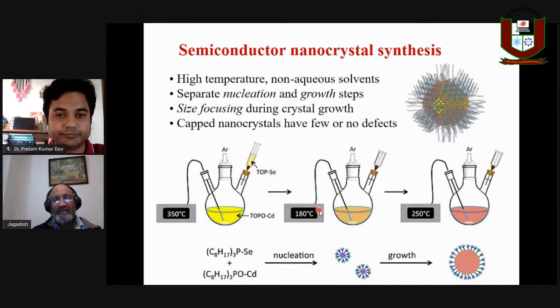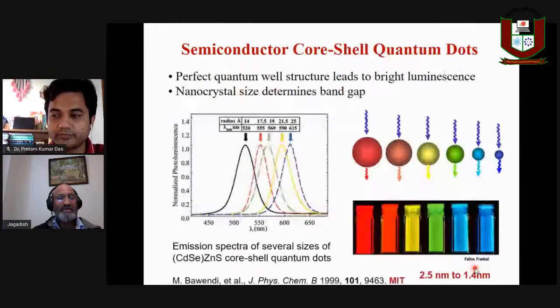And then if they start cooling it, then they stop growing. Also, if you introduce a particular chemical, the so-called ligands, then they attach to the nanocrystal, and the nanocrystal stops growing because it's not reacting with the surrounding media. That's how they're able to control these nanoparticles or quantum dots very precisely. And you can see a schematic of a quantum dot surrounded by these ligand structures which stop the further growth of these nanocrystals.